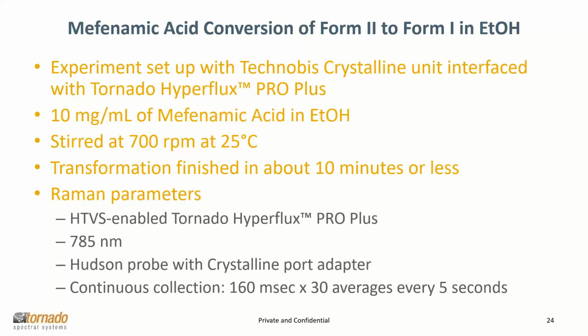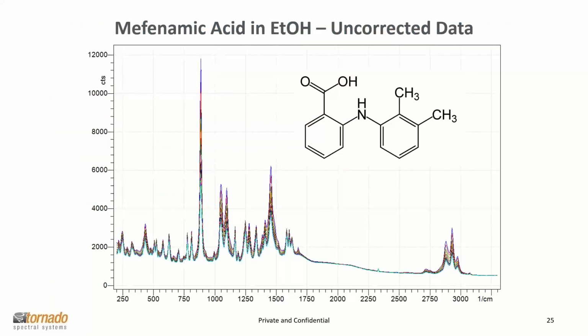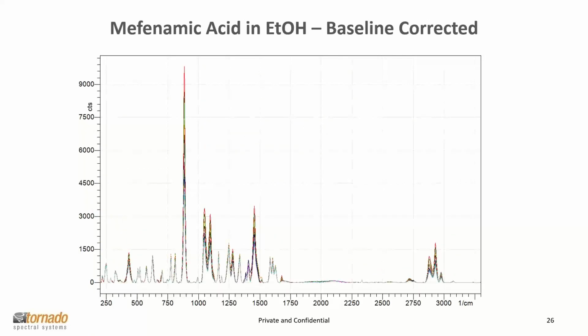You can see the parameters that were used, and these are fairly standard, except I will go to the bottom and just simply call to your attention the fact that continuous collection was used in this case with 160 milliseconds with 30 averages. So we were collecting spectra every 5 seconds for this experiment. You can see the resulting spectra that were obtained for this set of experiments. You can see there's a bit of a baseline effect here. And so if we do a baseline correction, we can get rid of that effect.